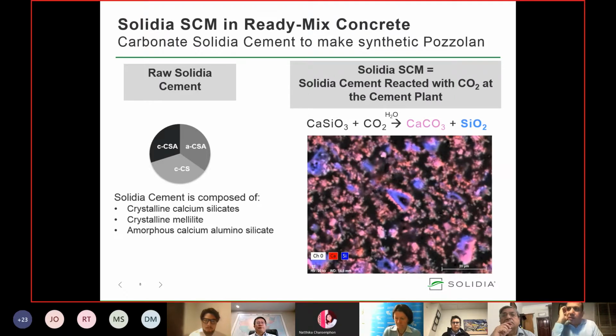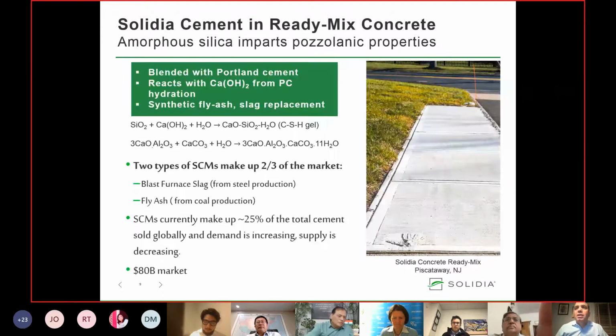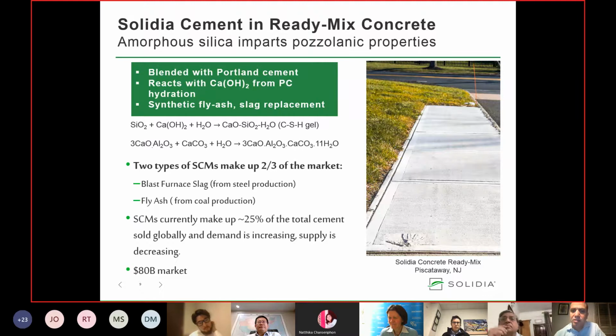In the micrograph, the colorful picture, you are seeing the reaction after the carbonation. The pink particles are the calcium carbonate and the blue particles are the amorphous silica. So why do we love amorphous silica? Because once you mix it with OPC, the amorphous silica is going to react with the calcium hydroxide that is generated during OPC hydration, and we are going to form CSH gel.